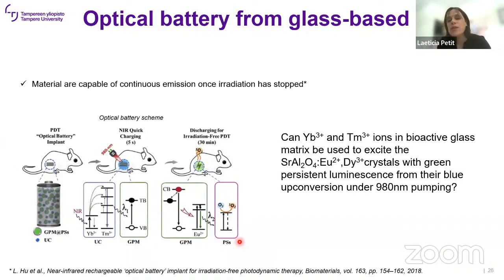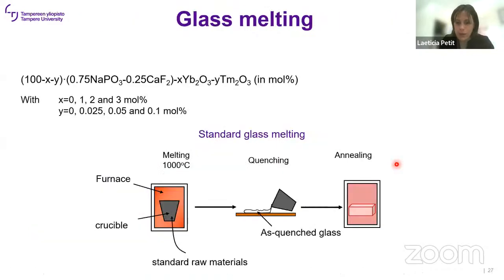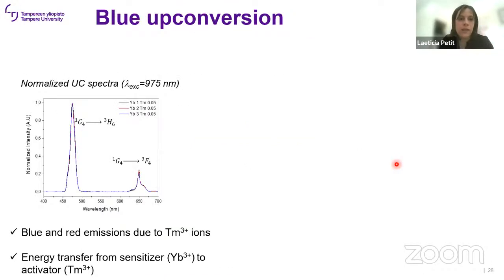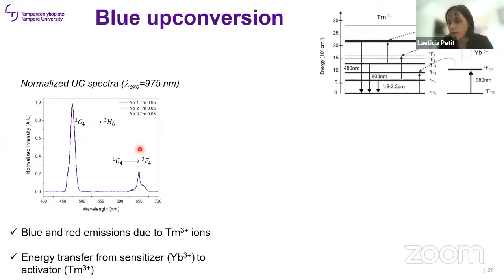So we wanted to check, can we do the same in a bioactive glass using ytterbium and thulium in the glass, and then add the crystal in the glass melt? Can the blue upconversion from the glass be strong enough to excite the green persistent luminescent crystal? This is the way we made the glass, and here you have the blue upconversion. The first step was to optimize the ytterbium and thulium ratio in the normal glass. We excited at 980 nanometer and looked at the blue upconversion, and we have the typical blue and red emission from the thulium, and this confirmed the energy transfer from ytterbium to thulium.